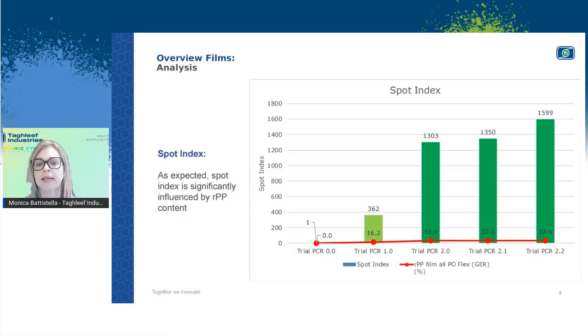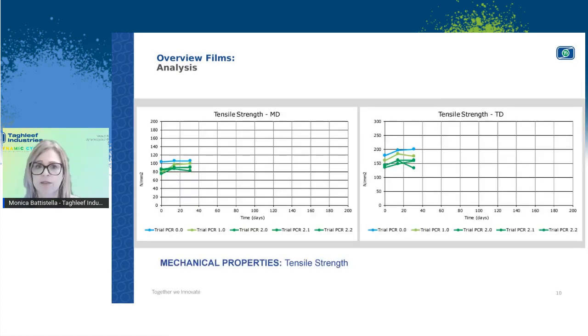This is showing exactly how the number of gels have increased starting from the sample which is indicated with 0.0 up to the sample which is called 2.2. So by increasing the amount of recycled content, the number of spots and gels was to increase. But again, as we said, it was not a parameter based on the assessment that we have carried out, which really could interfere with the final use of the film or make it not suitable for the applications which are actually identified.